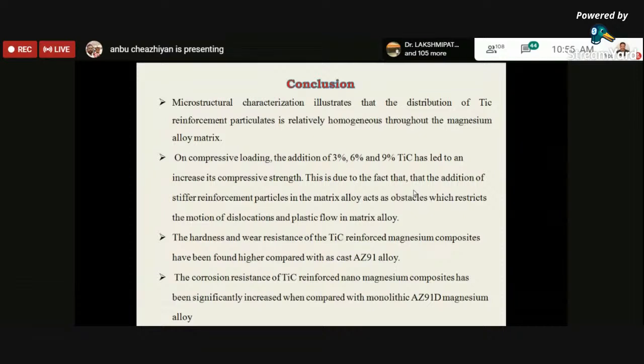So these are the conclusions that we have obtained. That is the microstructural characterization of titanium carbide. The titanium carbide particles are reinforced effectively, and they form a homogeneous distribution through the matrix. On compressive loading, the addition of 3%, 6%, and 9% titanium carbide has led to an increase in strength, as it restricts the plastic flow in the matrix alloy. That is the basic reason for the increased compressive strength of the composites.